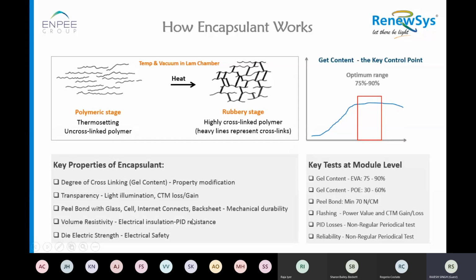So this block is actually the input property which is imparted into the encapsulant while making it by virtue of formulations. And the other boxes are the output properties, which are measured before we ship the consignment to customers. And these are a few things which should also be tested at the module level after the module is made. For example, gel content, peel bond, and flashing of the module, which gives how much wattage has been generated, or how much is the CTM loss or gain after making the module from cell to the final stage of module. And PID losses are also one property to be tested, because this gives power loss when modules are installed in the field in hot and humid conditions.